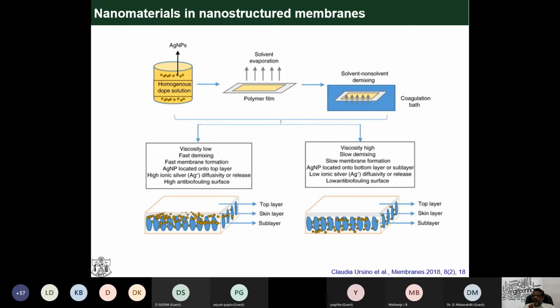Actually, I told you that modification of the polymers by using these inorganics is called mixed matrix membrane. If you use these inorganics to make the membrane, it should be a homogeneous solution. Then we make the membranes by thin film. What is different in thin film? The thin film doesn't have the pores. Membranes are having more pores. How do they create the pores? The solvent present in the solution evaporates, and they create the pores. Actually, we have to maintain the viscosity of the homogeneous dope solution. The viscosity of the homogeneous solution plays the main role in altering the membranes for different pores.